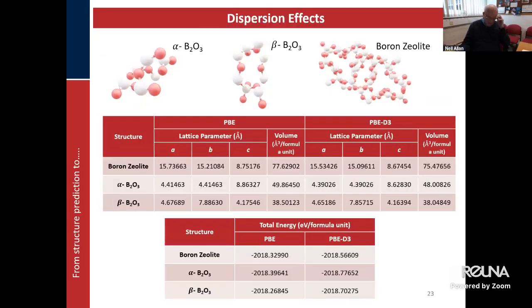A paper had appeared, which I actually disagree with, because in our original papers on the boron oxides we had ignored dispersion effects. They were using a program I'm not going to name, and I think there was simply a bug in the program they were using, because we have included dispersion corrections, and as you would expect for something as light as boron, they make a difference, but not a huge difference, and no qualitative conclusion of our work changes.